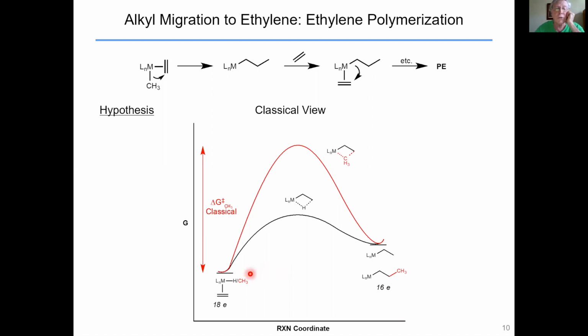If you think about a migratory insertion, the corresponding migratory insertion of a metal methyl complex has a barrier that is a lot higher than the migration of hydrogen. The bridging alkyl is much less stable than the bridging hydrogen. So now imagine if we choose a metal and ligand combination so that the bridging hydrogen becomes the ground state of the species, the most stable form of the species. Then the barrier to alkyl migration in that same species should be lowered. And so if we pick out a system in which the metal hydride is agostic, we would propose that the barrier to methyl migration in the same analogous species should be a lot lower.